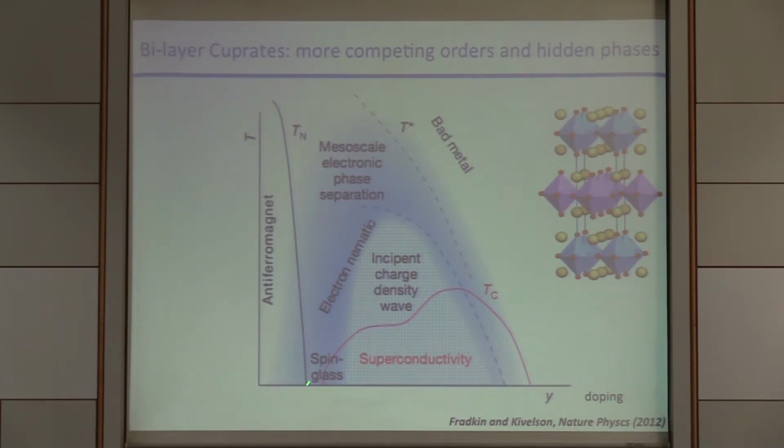You can see that there is a superconducting dome, a depression of the superconducting dome close to 1/8 doping, a mysterious charge and spin density wave that takes place here, some nematicity here, which changes every year, and then this mysterious T star line that defines a region of the phase diagram in which some people say there are preformed pairs that are fluctuating, other people say a different order sets in, but anyway, broadly defined. This is a gapped state that in many ways looks like the superconducting state, but it's just not superconducting, okay?